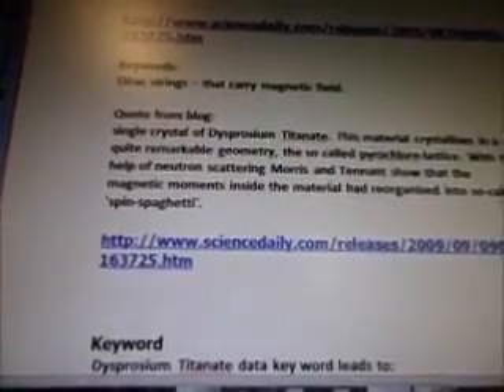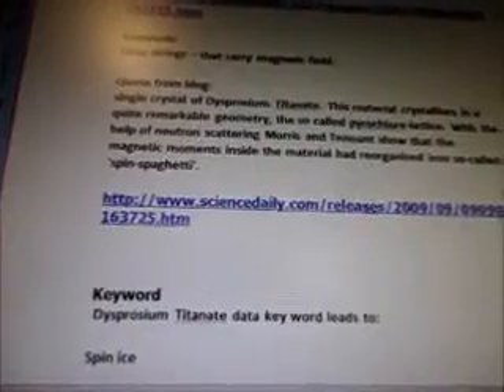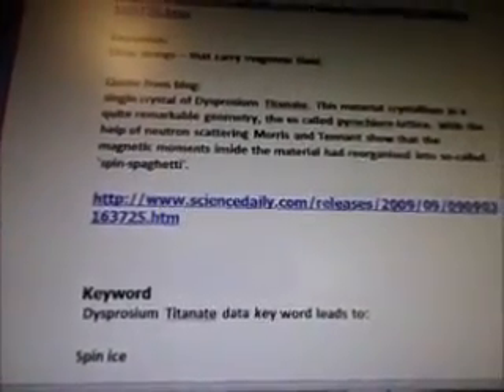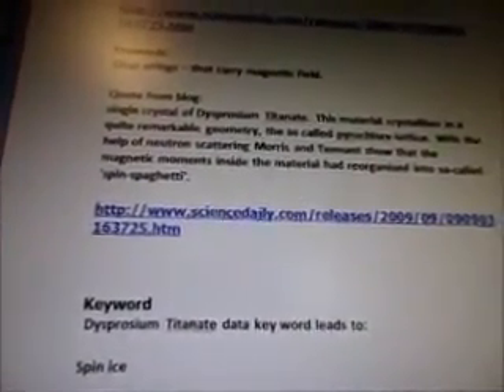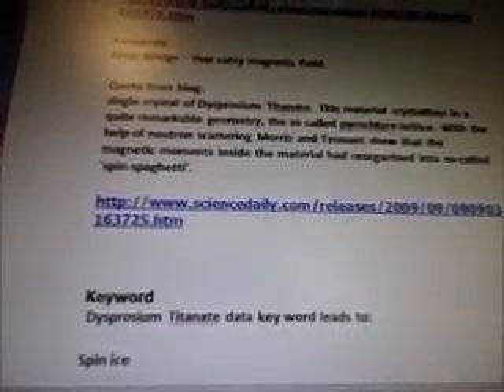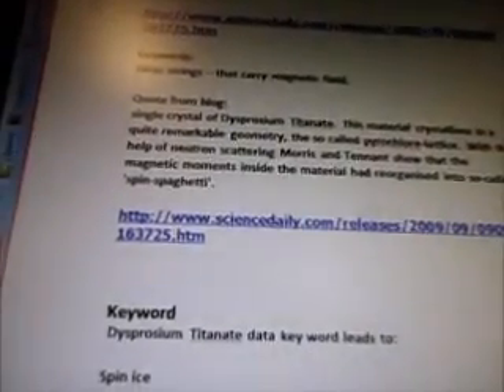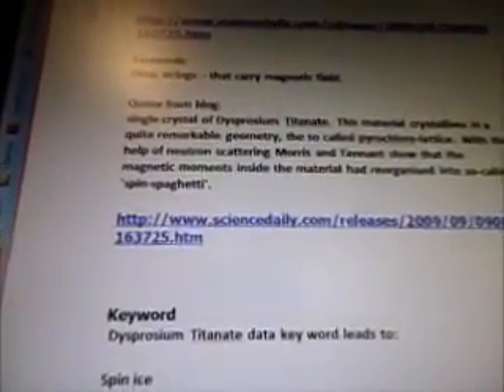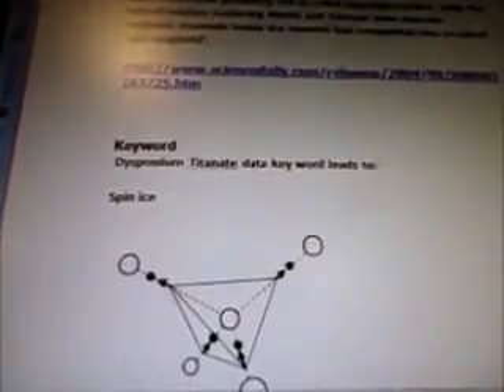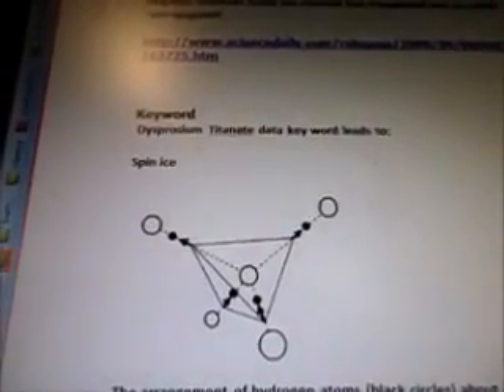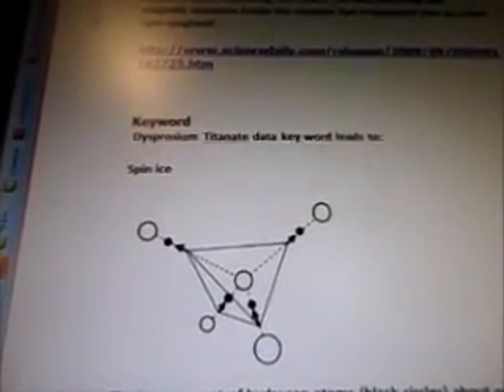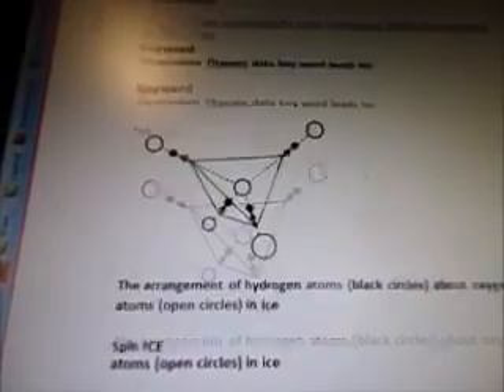Keywords are Dirac strings that carry a magnetic field. Quote from blog: single crystal of Dysprosium Titanate. This material crystallizes in a quite remarkable geometry, the so-called pyrochlore lattice. With the help of neutron scattering, Morris and Tennant show that the magnetic moments inside the material had reorganized into so-called spin spaghetti. That's from ScienceDaily.com. So the keyword is Dysprosium Titanate. That keyword leads to spin ice.